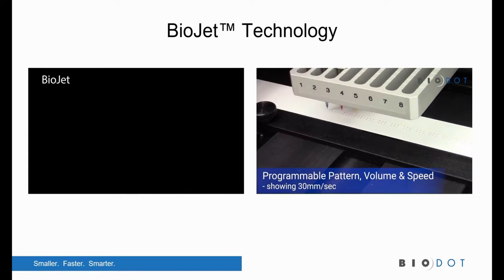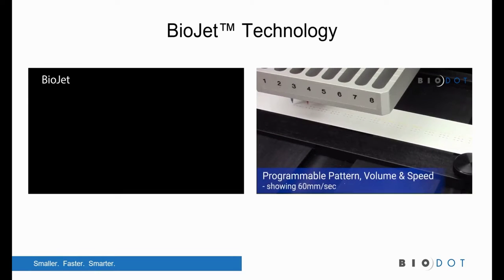3 different BioJet channels dispensing arrays on the fly of 20 nanoliter drops. The speed shown here is 30 millimeters per second. However, the speed can be run at a more vigorous 60 millimeters per second, which is shown here. Each one of these arrays would represent a separate test.